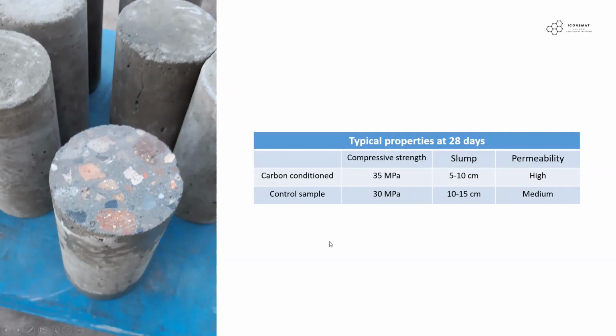These are the results that we got from mixing physically carbon conditioned recycled aggregate in concrete. These colorful aggregates that you see are actually the recycled aggregate. When you compare it with the control sample at the age of 28 days, you can see that we have a slight increase in the compressive strength and a considerable drop in the slump, which makes it a bit harder to work with. And the permeability is also higher in carbon condition, or say a concrete that uses recycled aggregates as a portion of it. These aggregates contain brick, which has a higher porosity, and thus the water absorption is usually higher.